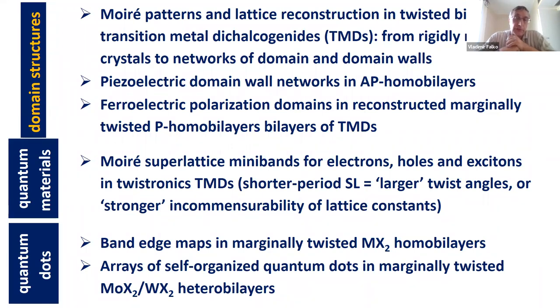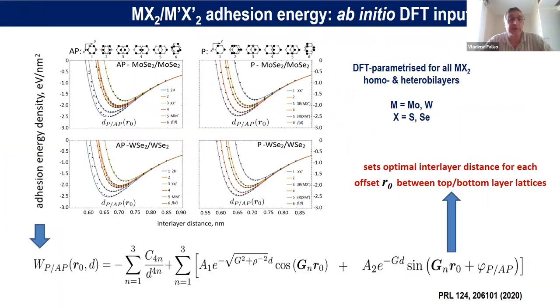For those, I'll show that there is an additional effect of strain, which is not present in homo bilayers, which comes through the hydrostatic strain, which has opposite sign in the two layers because they initially have slightly different lattice constants, which locally upon adjusting produces a hydrostatic strain of opposite sign in the two layers. And that effect has a very pronounced effect on the band structure, creating arrays of self-organized quantum dots, both for electrons and holes at the same place, so that we get self-organized quantum dot arrays for excitons as well. So this is my plan, and I start with the discussion of what happens with the structure.